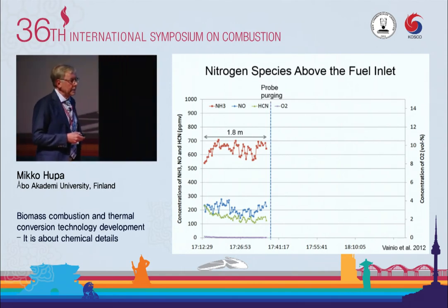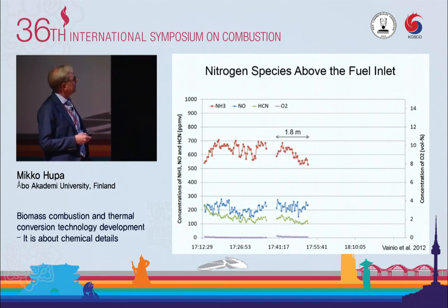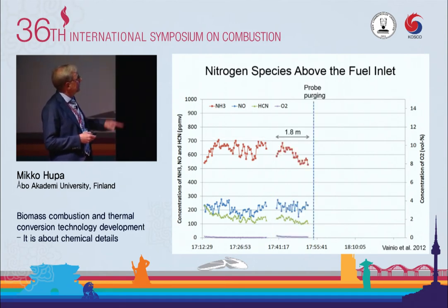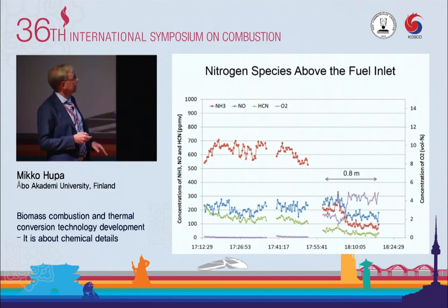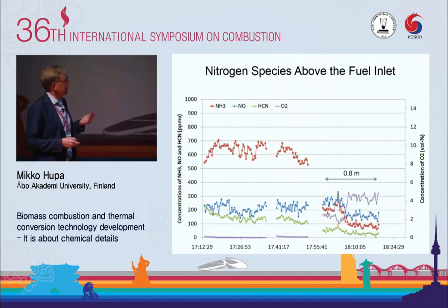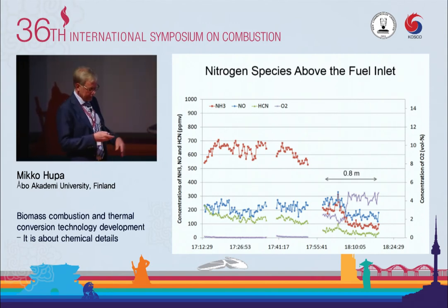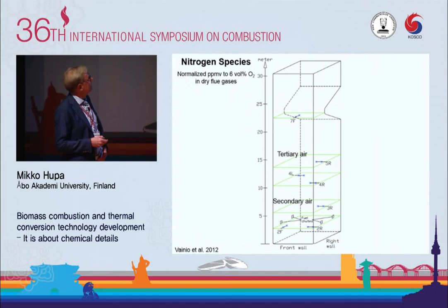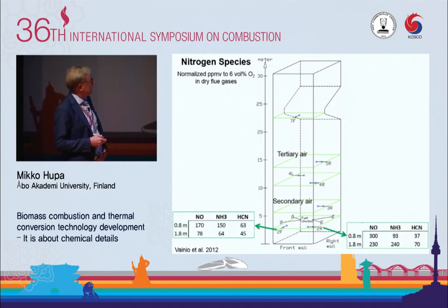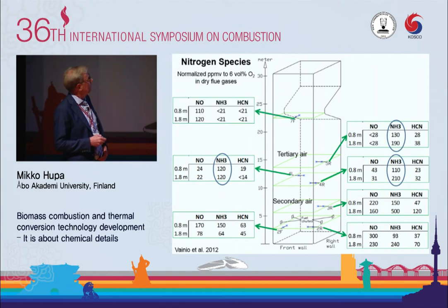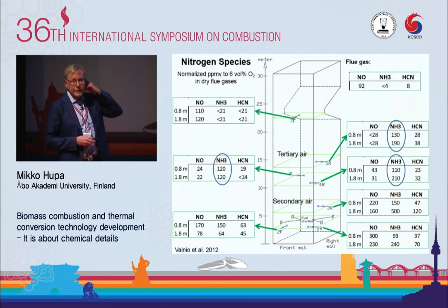And then we had to clean the pipe quite often and then get a new signal. Here, this is 1.8 meters into the furnace. Then we pulled it a little further back, so it was only 0.8 meters in, and we get another signal. And this we did in many locations in that unit. Here you see the locations. And there were a lot of interesting data. Here you see the lower furnace nitrogen species, and then we had them all over here. And finally, the flue gas nitrogen oxides, 92 ppm.